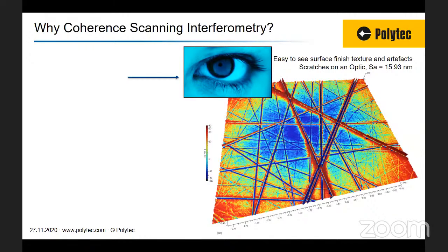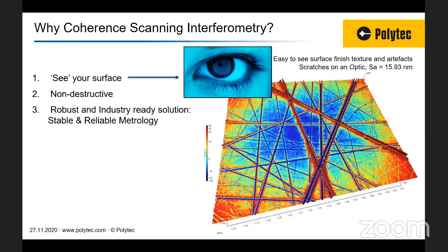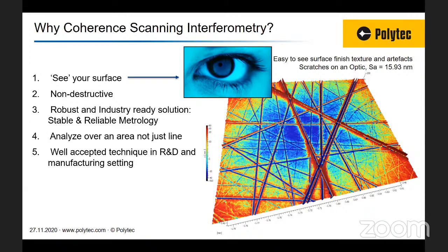So why coherence scanning interferometry? First of all, you see your surface. If you have a surface with scratches on it, it's very easy to identify these scratches. These particular scratches are in the order of 15 nanometers. Our measurement is non-destructive. The technology has proved very stable, reliable and robust. You can analyze over an area, not just a line. Our technology is well accepted in both R&D and especially manufacturing settings, where most of our sales to date go. We can measure a variety of materials, whether black, smooth, shiny, bright, dark, even combination surfaces. With our smart scanning, we can take care of all different surface types. And of course, our data is deterministic in Z.